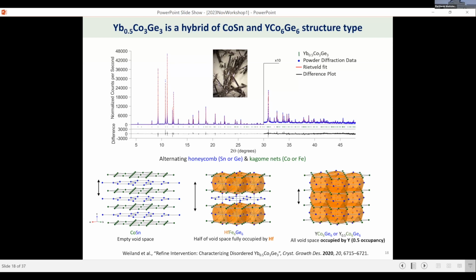But basically the hybrid structure is really a combination of both the cobalt tin and a 166 hafnium iron germanide. And if you look at the formula, it's similar to the 166, but it turns out it has to do with filling the void. So cobalt tin, in this case, on the very left, you basically have these void spaces that are not occupied.